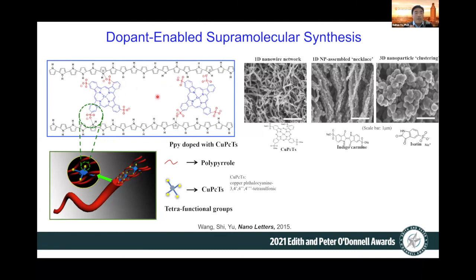So it's the first time in the literature that, without the need for templates, they can form this highly interconnected network of 1D nanowires. And then when you change to a different cross-linker, for example, from this tetrafunctional group to the bifunctional group, indigo carmine, and to the smallest one, this monofunctional group, you can see the clear transition from this 1D nanowire to this 1D nanoparticle-assembled necklace to these 3D nanoparticle clusters. So you can see the supramolecular self-sorting mechanism can play a very effective role in controlling their structure and morphology.